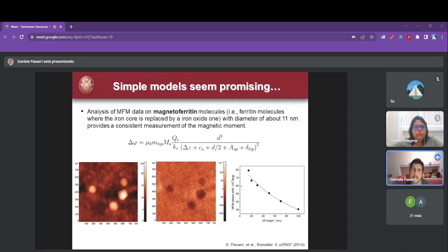Of course, we started with very, very small particles, magnetoferritin, which is ferritin molecules where the iron core is replaced by an iron oxide core. And we obtained those phase shifts. Note that dark phase shift means attractive. In this case, there was no external magnetic field. The magnetic field was produced by the tip, so the tip attracted the iron core. And this is the standard model you would expect for two dipoles interacting, and the result seems quite good.